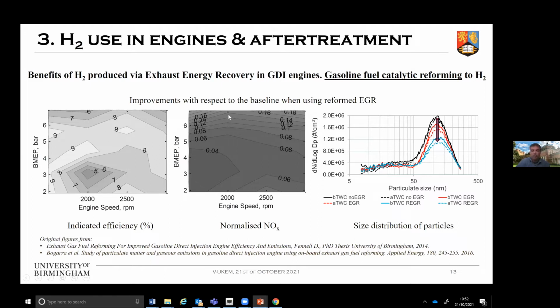We were able also to reduce NOx emissions. Again, these numbers here represent the reduction. So 0.06 means that we were able to reduce NOx emission by 94%, 0.12 that we were able to reduce it by 88%, as well as obtaining a reduction in the particle emission levels.